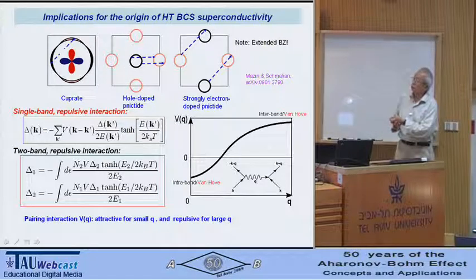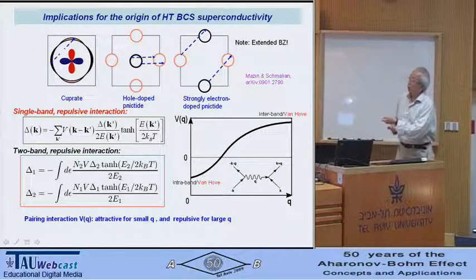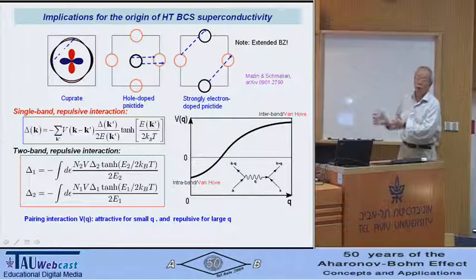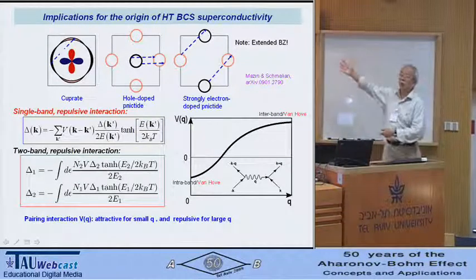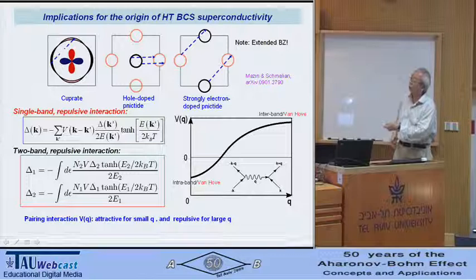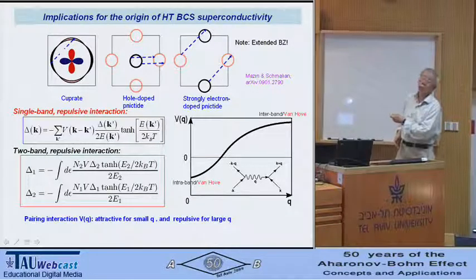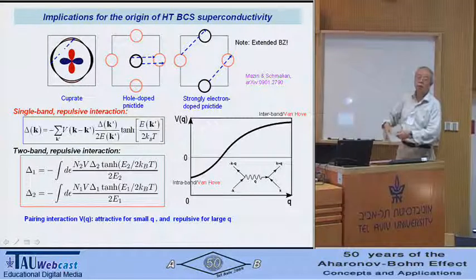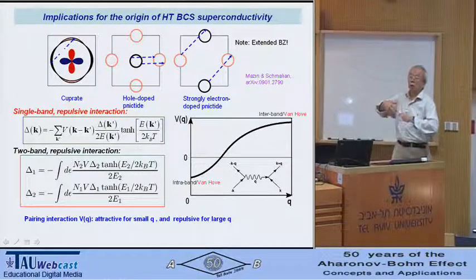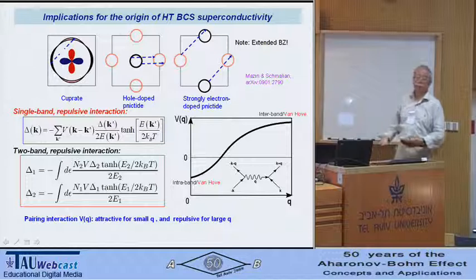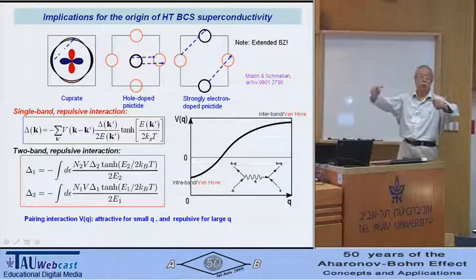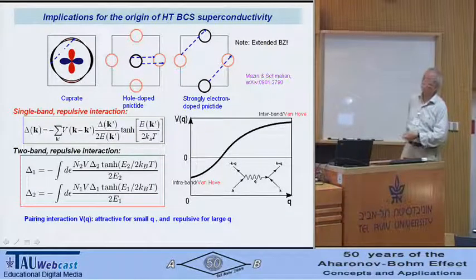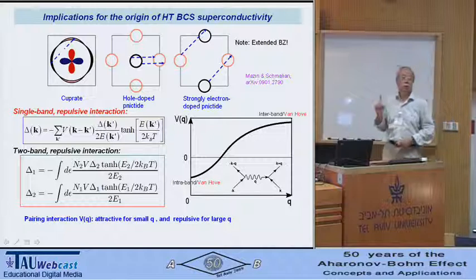This has to be attractive, relatively attractive. The whole thing can be repulsive, but this has to be relatively less repulsive, and here it's repulsive in this case. Now, in the iron pnictide, let's say we assume the simplest case, you have two bands, another two Fermi surfaces. Then you get the same conclusion. The sign should be reversed. So that's consistent with S plus minus.